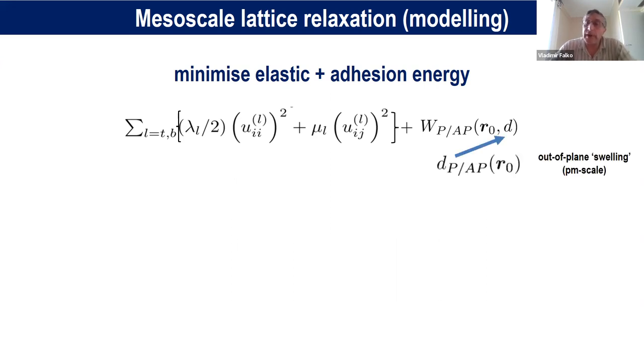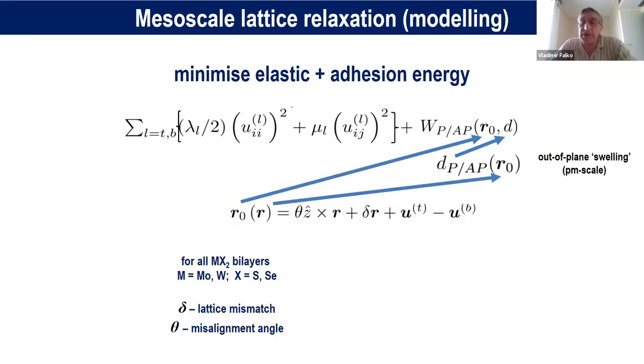Locally, it happens by a bit of swelling for each of the offsets, and then adjusting by displacement inside of the top and the bottom layers by deformations that, of course, cost strain energy. Altogether, if we minimize this, we get the overall structure of the deformations and the overall structure of the atomic positions in both crystals.